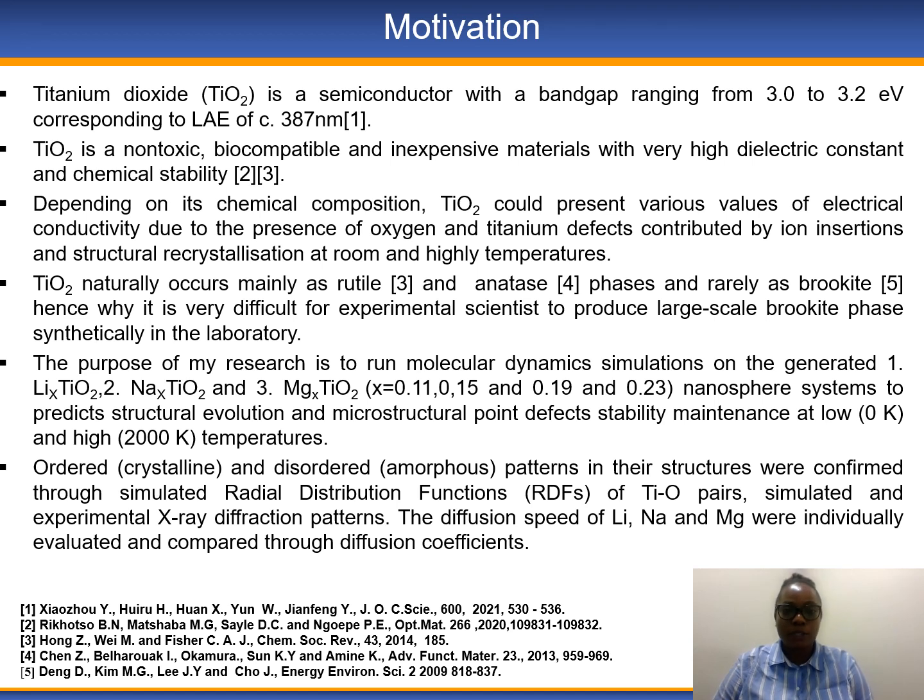Titanium dioxide is a non-toxic, biocompatible, and inexpensive material with high dielectric constant and chemical stability. It is a semiconductor with a band gap corresponding to the light absorption edge of 387 nanometers. It mainly occurs as rutile and anatase and rarely as brookite in nature, which is why it is very difficult for experimental scientists to produce large-scale brookite phases synthetically in the laboratory.